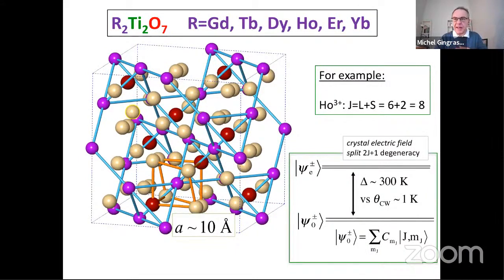Using language for the experts, the g tensor that characterizes these systems in ESR-type language is such that it has two components, and the local Ising component of the g tensor below 1 Kelvin is something like 500 to 1,000 times larger than the other components of the g tensor. So we're dealing with Ising systems for holmium and dysprosium.